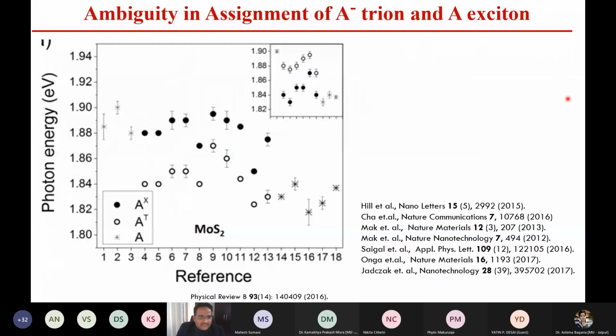And it is not clear. There is an ambiguity in assignment of the A- trion and A exciton peaks. You can see this is published in this particular paper, and a lot of people have tried to understand it, and it's very difficult to distinguish, particularly for MoS2, where this A- trion will be there and where the A exciton peak will be there.